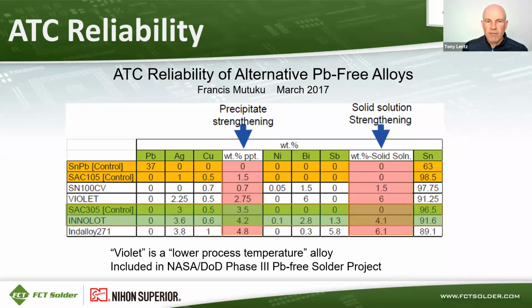SN100CV, however, has a fairly low concentration of precipitate elements, 0.7 copper, and 1.5% bismuth is the solid solution strengthening element within that alloy. Violet has mainly solid solution strengtheners as well, 2.75 versus 6%. And then if you jump down to Innolot, you see Innolot almost has an equal amount of precipitate strengthening at 4.2% versus solid solution strengthening elements at 4.1%. And Indalloy 271 has a very high concentration of both, but a higher concentration of solid solution strengthening elements.